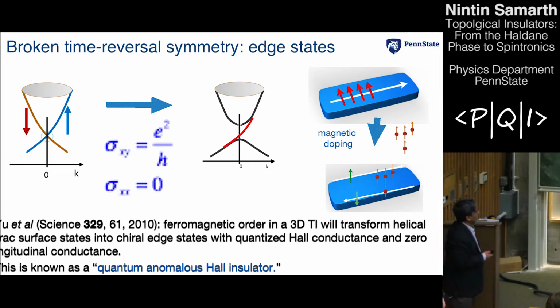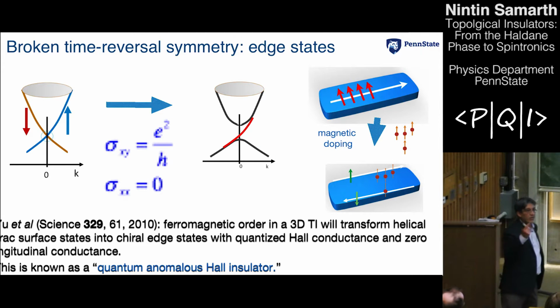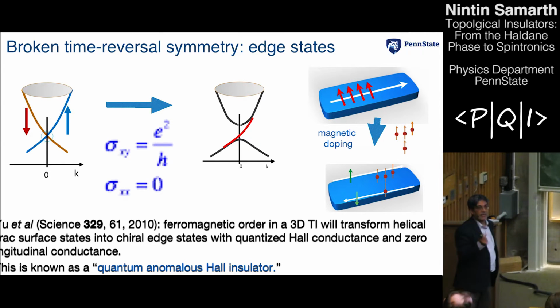And they argued that if you take a three-dimensional topological insulator and you make it ferromagnetic, then you will, as I argued on the earlier slide, go from a situation like this to something like this. But they argued that in this gap, you will actually get a state that's no longer this helical Dirac state that we talked about on the Dirac cone, but rather a chiral edge state. So this will be like the Haldane state. It's something that propagates around the edge and has chirality to it, right? But without any Landau levels, without any magnetic field.